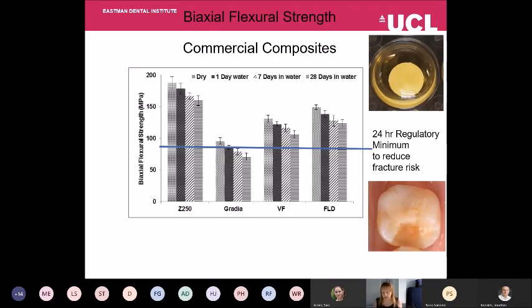One of the issues is that if we have very hydrophilic components, they draw in water, and that can cause strengths to go down. If we look at commercial materials, they all go down in strength somewhat in about the first 28 days after placement in water, due to water absorption. The materials we've got decrease in strength by similar amounts over 28 days, but then form an equilibrium strength.